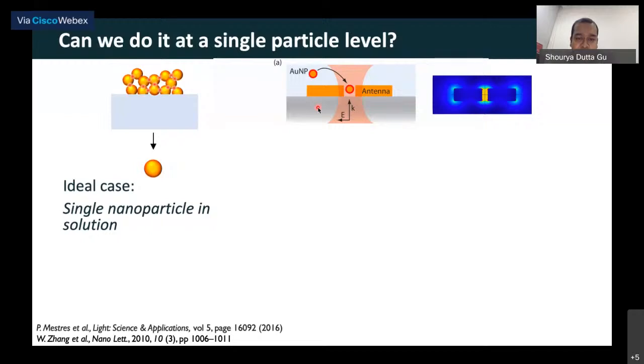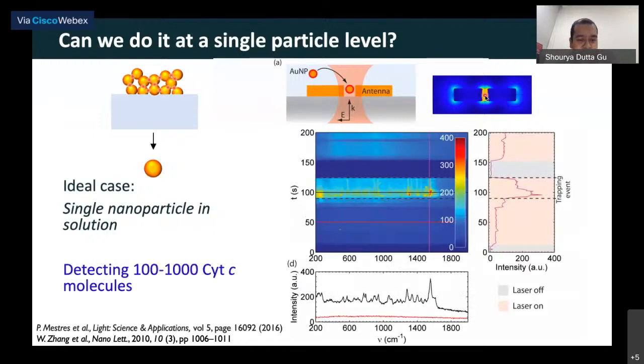So here we have two different gold bars shown by the yellow cuboids, which basically form a plasmonic tweezer. Now, if you shine the light onto this structure, what will happen is you will have a high field which will actually try to get the particles from outside the trap to inside the trap and get them between these two cuboids in the center of it, right? So this is the experiment that we did. Again, the horizontal axis is the wave number, the vertical axis is the time. Now the strength of the tweezer, or how hard you are holding it, depends on how much intensity of light you're sending to this particular structure, right?